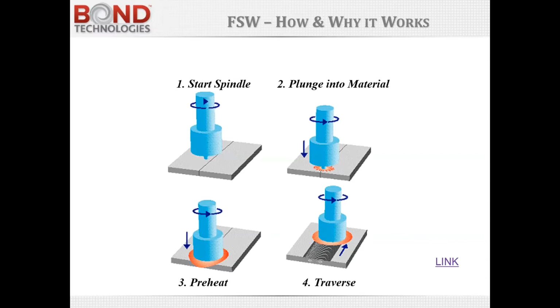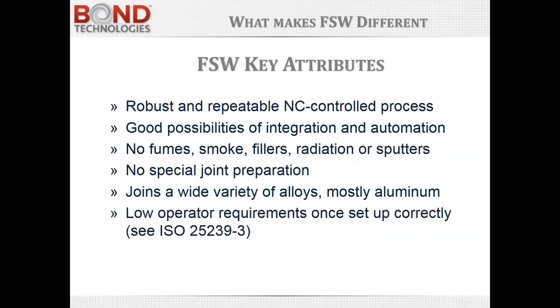There's a fairly complex motion that occurs during this traverse, consisting of both a fairly aggressive forging force in the downward direction, and a mixing in the horizontal direction to stir these materials side to side. But there's also a significant vertical component to the mixing that causes a high level of grain refinement in the material, as well as a strong joint. Some of the key attributes are that this is a numerically controlled process, so it lends itself to integration and automation.